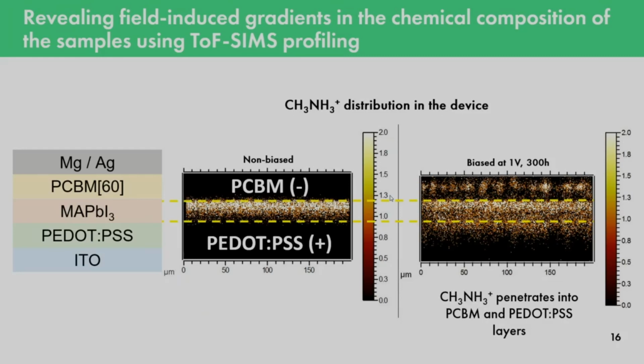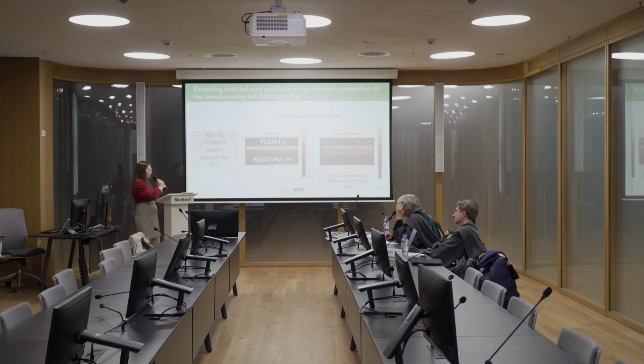And if we talk about migration into the PEDOT:PSS layer, it can't be because of the applied electric field, because it would be strange if a positive charge migrated to the positive electrode. So the only explanation is that inside the perovskite layer we have this redox process, which was mentioned in the mechanism. We had some formation of methylamine, and this methylamine reacted with polystyrene sulfonic acid, and thus migrated in the form of a volatile which reacts with the acid. It migrated into the PEDOT:PSS.